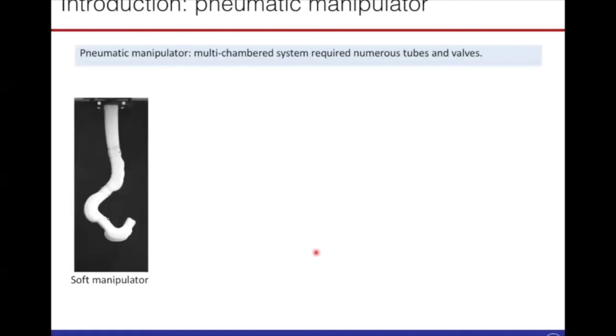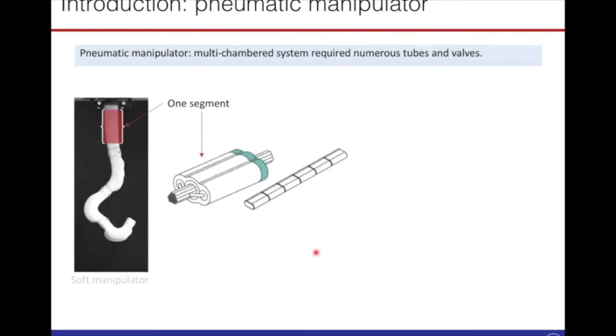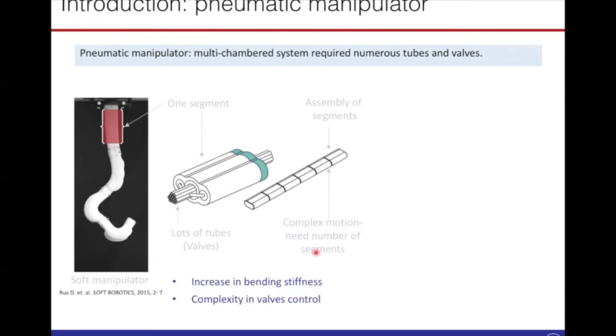Here is a work done by an MIT group where they developed a soft manipulator. If you look at the soft manipulator, generally they are multi-chamber segmented systems, meaning each segment will have 2 or more chambers. And of course, if you need a complex motion, then you need a number of segments, and then you will increase the tubes and valves that are needed to control this actuation or the deformation. So generally speaking, it can increase the complexity, and sometimes these soft tubes could increase bending stiffness at some locations.